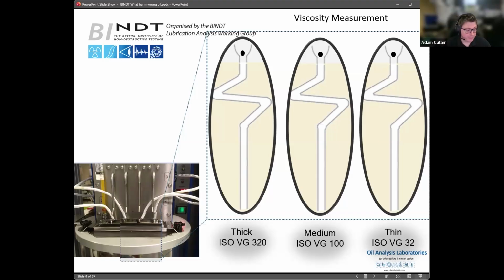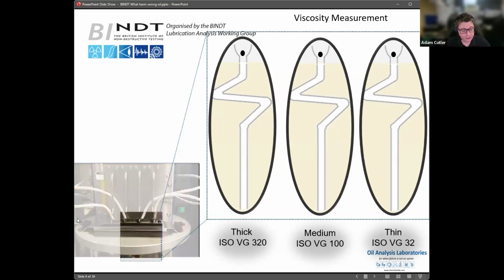So if we take this bath here, on the left-hand side I've got three tubes I've highlighted. I'll highlight them for you on screen. If we put some oil down each of these tubes, we can see that the one on the right-hand side actually hit the bottom before the first one, although that started first. The reason for that is a much thicker oil has more resistance to flow, and so takes longer despite starting earlier.